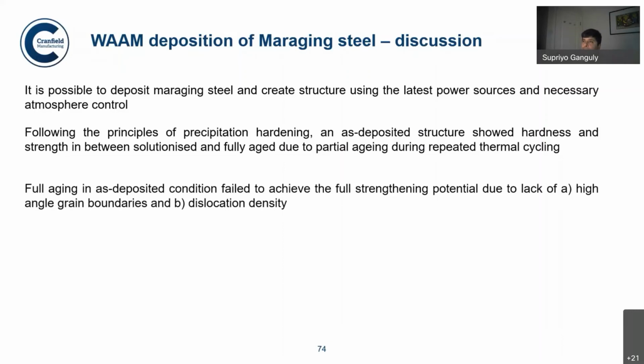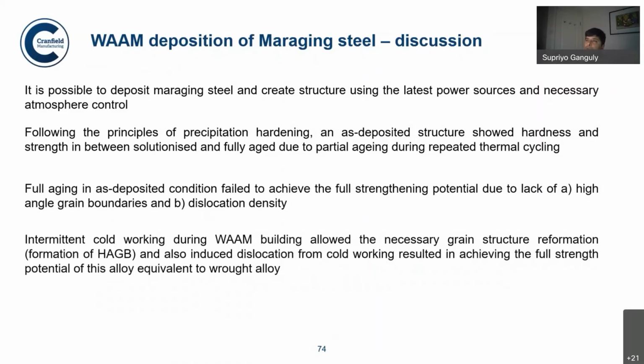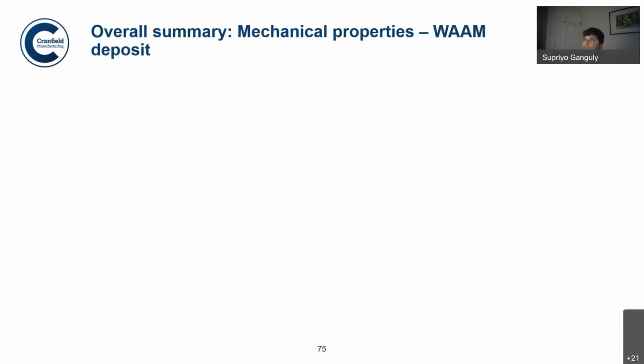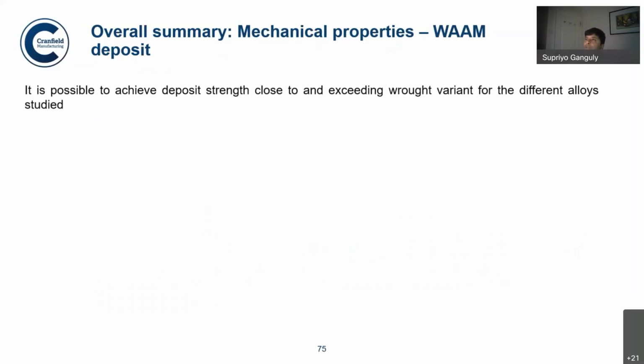So we identify that probably the lack of high angle grain boundaries and lack of dislocation density are not conducive to solutionizing the structure to the extent that is possible with rolling, basically. So cold working obviously gives the necessary grain structure reformation, introduction of high angle grain boundaries, which will allow a proper solutionization, and thereby the response during aging will be much better. So overall summary, I would say it is possible to achieve deposit strength close to or exceeding the wrought variant of different alloys.